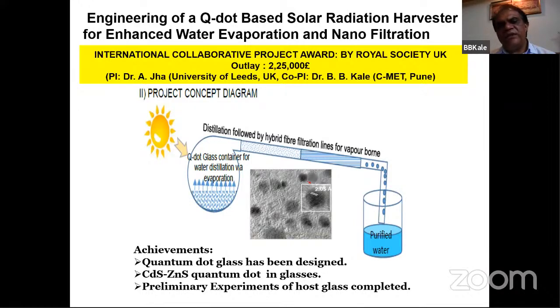Still some work is going on in this, because this quantum dot, the bismuth telluride, bismuth sulfide, we have inside the glass. If sunlight falls on these glasses, because they absorb the IR rays, heat is generated and the boiler gets heated up to 90 degrees centigrade, and then we purify the water. So this is the concept. Now we have made a setup in IIT BHU of this kind, where we can take larger trials of this glass.